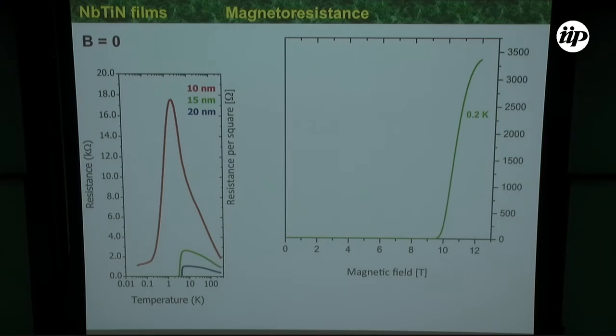Now, magnetic field. I am applying magnetic field and what I see. Now for this film, 0.2 Kelvin, 200 millikelvin, one curve for this. This is axis resistance per square. Now let's go. A little bit larger temperature, a little bit larger. I will not put all curves in order not to crowd, but it is only for you to catch the scale in the magnetic field. BC2 here, upper critical field is close to 11 Tesla.